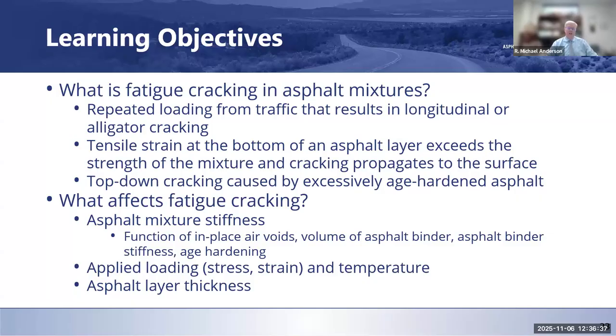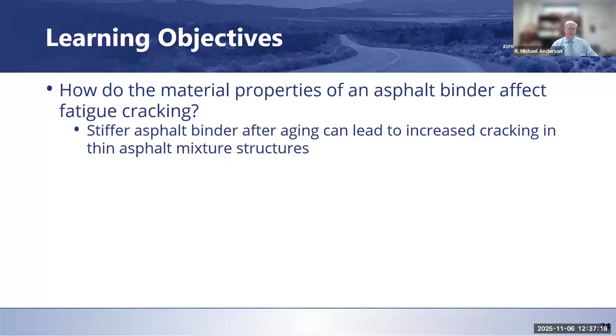So what affects fatigue cracking? Mixture stiffness, which is a function of in-place air voids, the volume of the asphalt binder, stiffness, and age hardening. That may not even be a complete list of what affects mixture stiffness, but certainly those are key factors in what the mixture stiffness in service looks like. The applied loading is going to affect it. How much traffic you've got on it, how heavy is the traffic, so what's the strain that's being transferred down to the bottom of the layer, and what's the temperature? That's going to matter as well. It impacts the stiffness, it impacts what that strain is going to do. And then the asphalt layer thickness as well is going to matter. Those are all going to play into it.